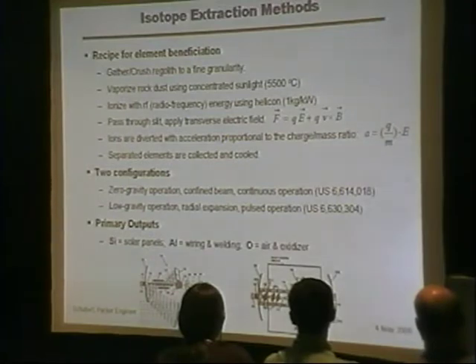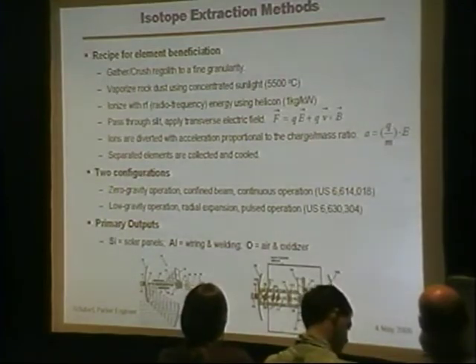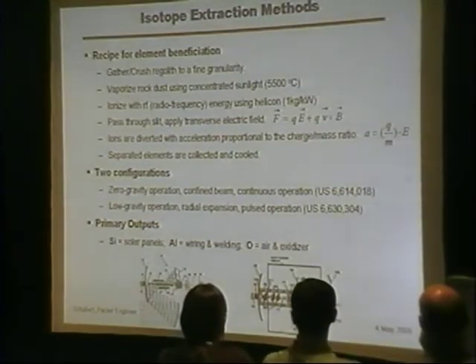There's 2 configurations that are envisioned here. The first one is a zero gravity operation, where you're in a L4 position, for example, and you use a collimated beam with quadrupoles, and then be able to separate this out in a continuous operation. For a lunar operation, for a quick and dirty brute force way of doing isotope separation, we can do a radial expansion. You have a tremendous amount of loss of the material and use pulsed operation, but you can still get a reasonable amount of this material out.